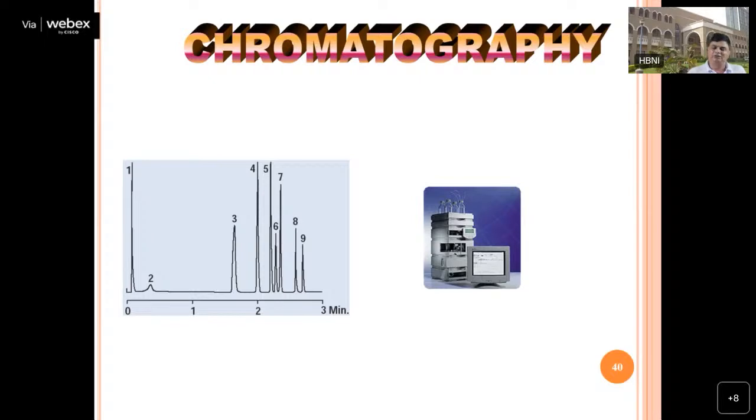No, actually, this is a common practice. For example, suppose you have a groundwater reference material in your lab, and you are doing the analysis of cadmium, but cadmium is not in the certified elements. It contains iron, cobalt, nickel, chromium, but cadmium is not there. So what you can do is spike the sample with cadmium. At least then you have a matrix-matching standard. That we call an in-house reference material.